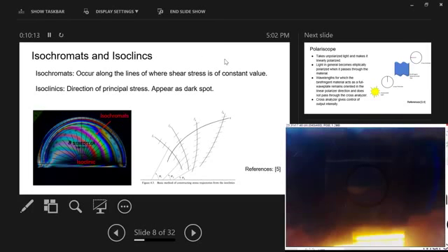The reason why there's separate wavelengths on each of these patterns is due to this constant phase delay for each wavelength. So instead of thinking of this as a uniform crystal, really what you should be thinking about is each section of the plastic is its own segment of a crystal, so that it has this continuous property of phase retardation throughout the material.